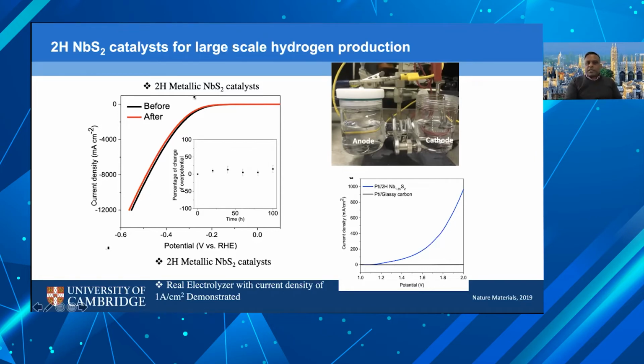And so we made some metallic niobium disulfide catalysts, and we found that it was possible to achieve very high current densities, on the order of a few amps per centimeter squared. We then fabricated electrolyzers to actually split water, where the cathode was this niobium disulfide, and the anode, just as a reference, was platinum. We're able to generate hydrogen with current densities of up to 1 amp per centimeter squared. This is quite important because in order for these materials to be used as real catalysts, they have to work at very high current densities and generate hydrogen at production scale.